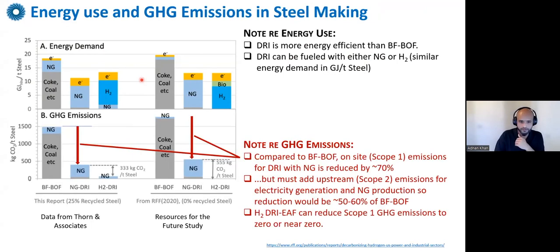DRI route. But then when we look at GHG emissions, and these are basically scope 1 direct emissions, compared to the traditional blast furnace, basic oxygen furnace route, on-site emissions could be significantly reduced by the transition to a DRI route. So when you transition to natural gas, you could potentially reduce emissions by about 70%. If you add upstream emissions related to electricity generation, natural gas production, we're looking at emission reductions of about 50 to